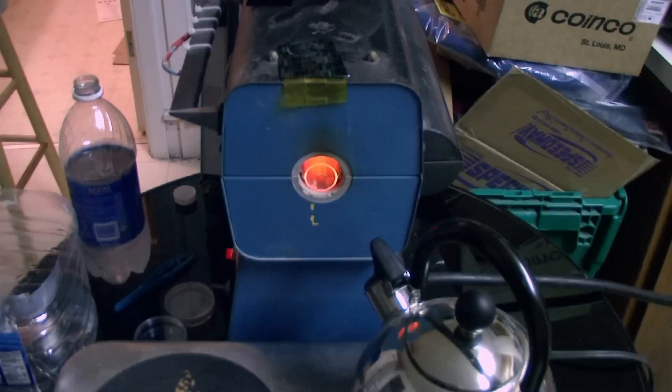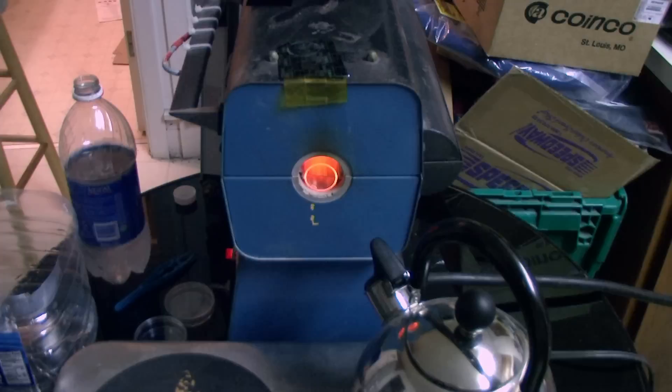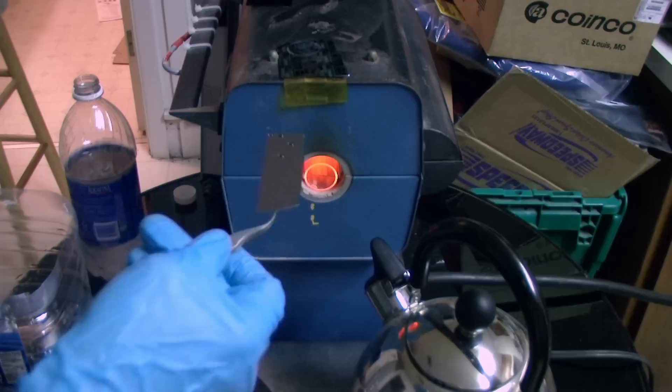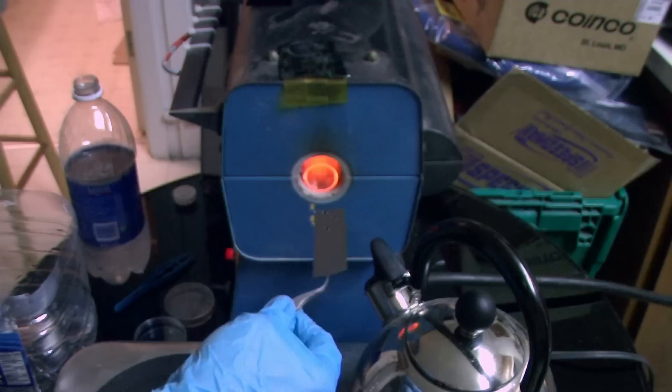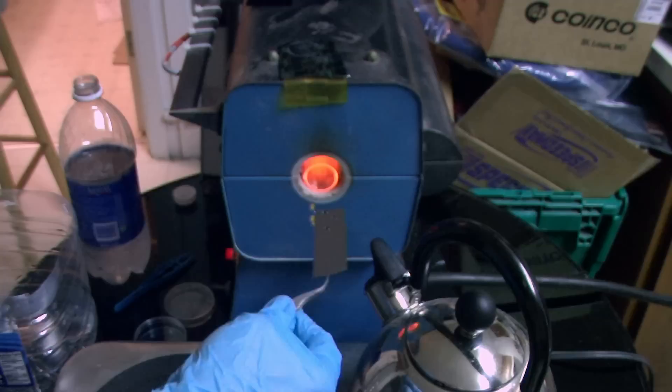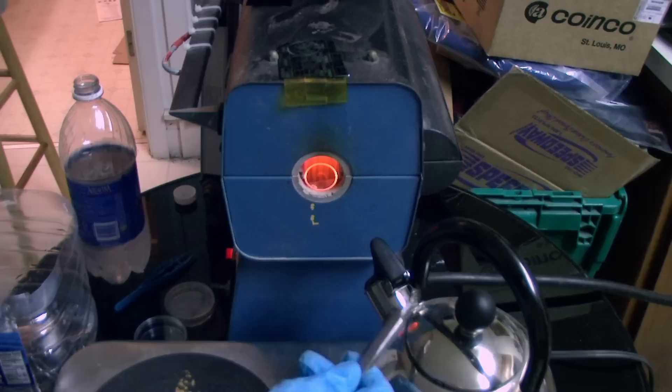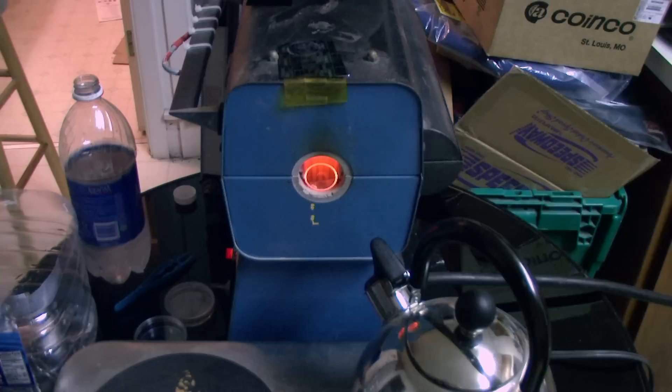I figure you guys would like to see loading of the wafers. So I flipped up the little piece of wafer that I used to cover the end of the tube. There's the quartz tube in there. Here's a wafer piece held with my stainless steel tweezers contaminating everything. You know, I made working devices, so it's not that big of a deal. And I just slide it on in there. And once I have all these pieces in there, I will turn on the tea kettle and make some steam and just let it blow up in there. The steam will accelerate the oxide growth, so I don't have to wait here an eternity for the thick oxide to grow. If you just do it in the normal atmosphere, it grows really slow.